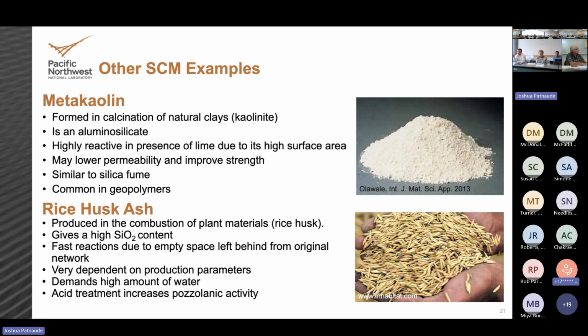Well, what some very ingenious people have been able to do is take the husks from rice, and when they burn it for energy sources, the resulting powder has pozzolanic activity. So rice husk ash has been an emerging supplementary cementitious material, especially in Southeast Asia, and showing as a promising candidate to replace fly ash as we see global fly ash amounts start to decrease. And this could be a possible replacement.